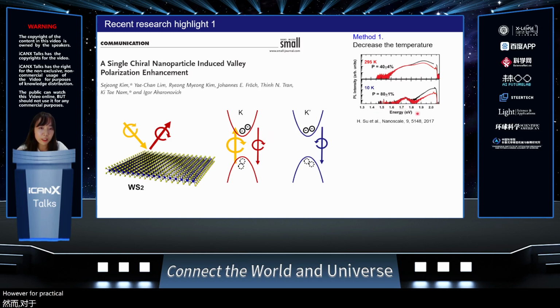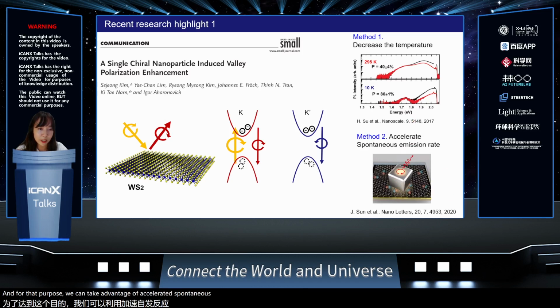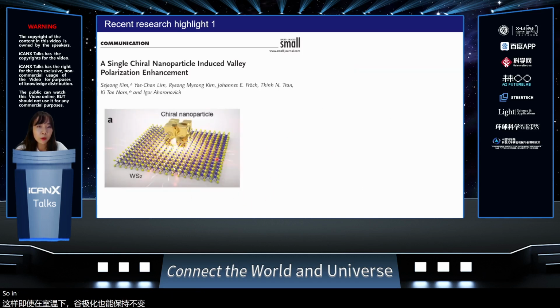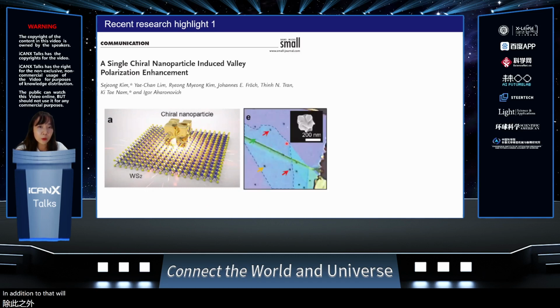However, for practical valley devices, it would be ideal to develop a device which operates at room temperature. And for that purpose, we can take advantage of accelerated spontaneous emission rate. If the spontaneous emission decay process is faster than the phonon decay time, then the valley polarization can be preserved even at room temperature. So in our work, we took advantage of fast spontaneous emission rates due to the plasmonic effect. In addition to that, we utilize chiral nanoparticles so that we could enhance the valley contrast further.